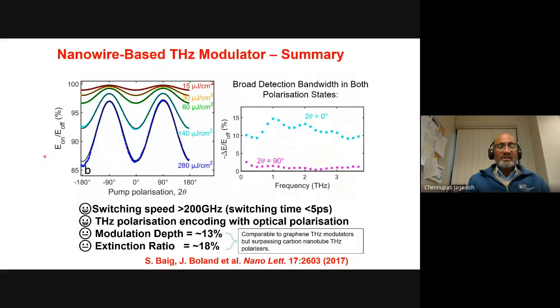So you can see, to cut the long story short, the on-off ratio of these polarizers as a function of the polarization angle. The largest modulation takes place at 0 degrees, indicating that's where the absorption is taking place, and of course it also depends on the laser power. And at 90 degrees, you expect small modulation. That's what we have seen.